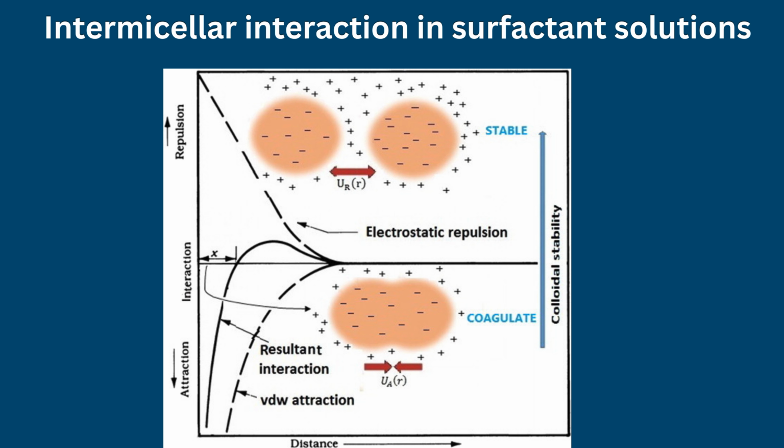At low temperatures, strong hydration of hydrophilic groups leads to repulsive interactions, stabilizing the solution. At elevated temperatures, dehydration of hydrophilic moieties reduces repulsion and enhances attractive interactions, van der Waals and hydrophobic forces. When attractive interactions dominate, for example, when the interaction parameter becomes negative, phase separation occurs, resulting in a cloud point. The process is largely entropy-driven, as dehydration releases structured water molecules into the bulk phase, increasing overall disorder.